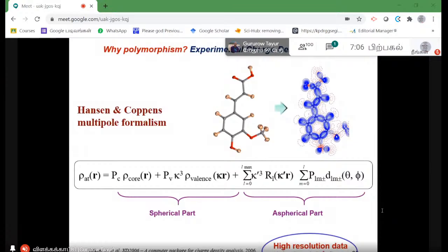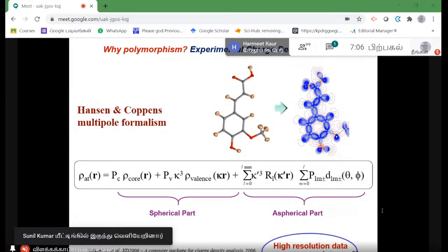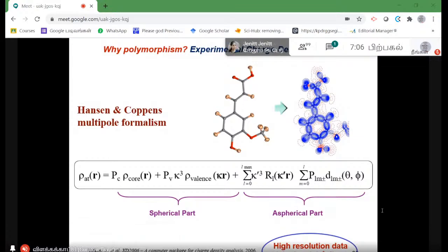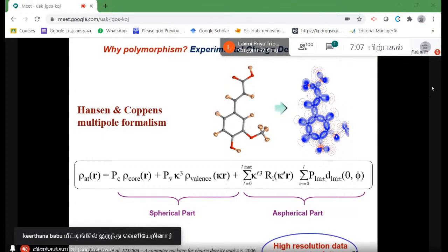And the aspherical part will tell you how the distribution of the electron density goes away from the given atom. So effectively, the atom is taken out, and whatever is remaining after the atom is taken out is referred to as the deformation density. So this is how the molecule is deformed in this particular crystal structure. So you can see that if you consider this oxygen atom, you see the so-called lone pair. We always refer to the lone pair in chemistry, and then talk about its reactivity and so on. We can actually see the lone pairs in some sense with the so-called deformation density. So this tells us the direction in which the two electron density regions are available. So any one of them could now be hydrogen bonded to the next molecule.